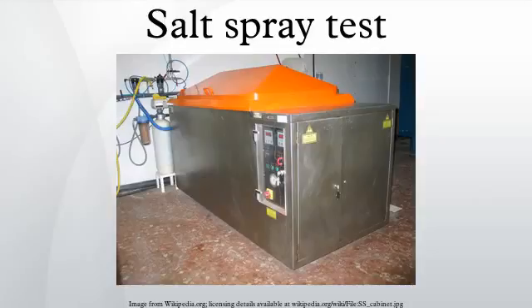For example, pre-treated plus painted components must pass 96 hours neutral salt spray, to be accepted for production. Failure to meet this requirement implies instability in the chemical process of the pre-treatment, or the paint quality, which must be addressed immediately, so that the upcoming batches are of the desired quality. The longer the accelerated corrosion test, the longer the process remains out of control, and larger is the loss in the form of non-conforming batches.